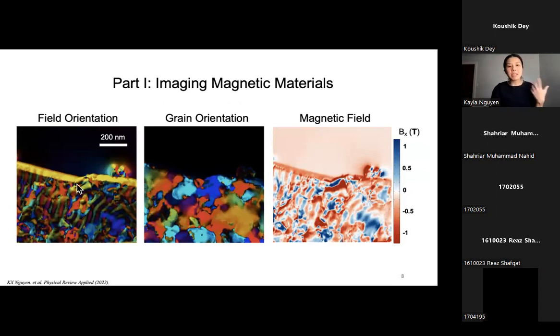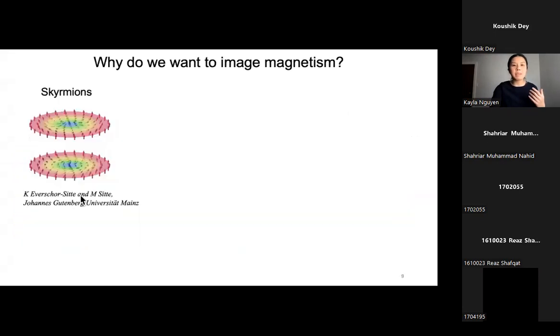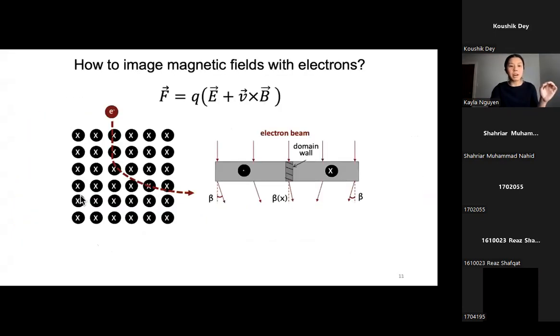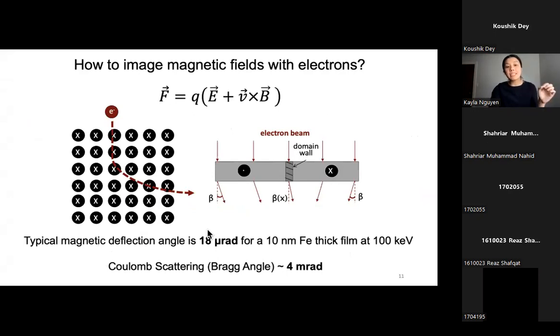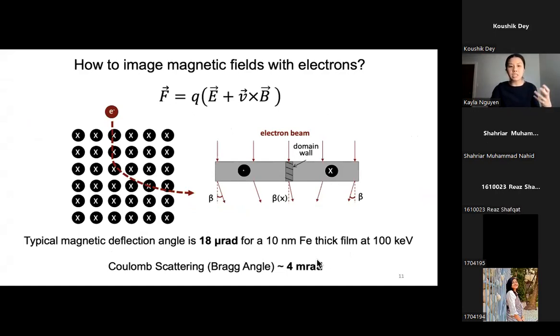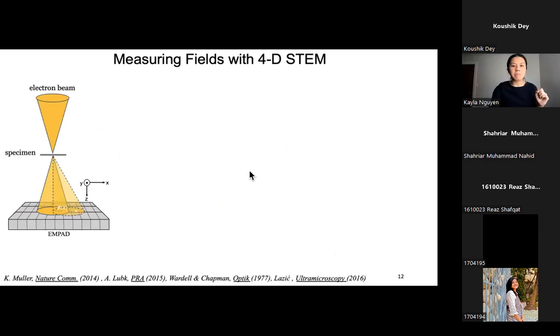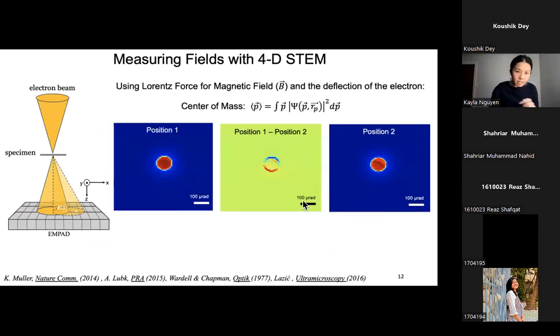So it gets a little bit complicated, but what you can assume is that magnetic field deflections are quite small, on the order of tens of microradians, whereas your electric field deflections are on the order of milliradians. If you change your experimental parameters, you see how the scale bar is 100 microradians. So if your magnetic field is only going to shift on the order of 10 microradians, your electric field is going to shift way more than that. It's going to take your center of mass image off the board. And so because the shifts are so different, you can actually separate them in experiments.